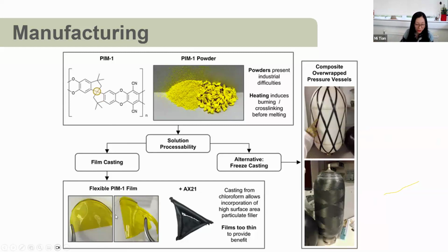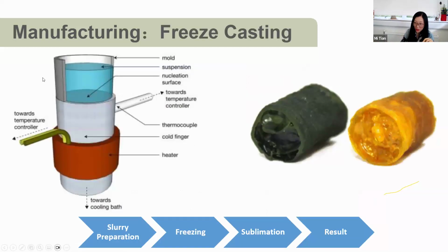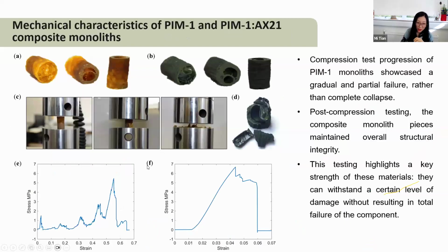So that is one method we explored. We used the free film casting, and then we realized the thin film is not sufficient to provide enough hydrogen storage capacity. So we need to shape it. And then we use the freeze casting method to make a monolith. So those are 2 monoliths we are making, which significantly increased the capacity. And we evaluated the mechanical properties of monoliths, which can satisfy the hydrogen storage tank application.